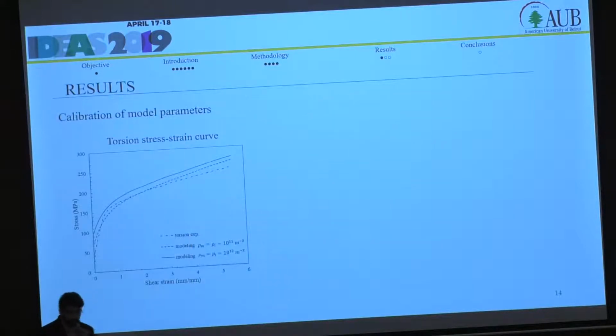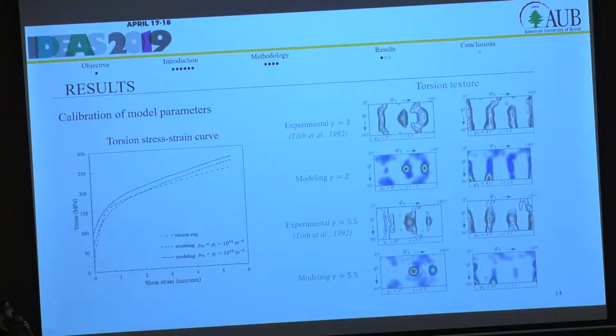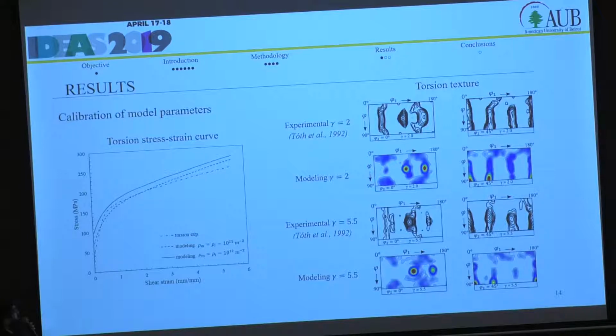Finally, in order to calibrate our model parameters, we have some model parameters that need calibration. Torsion experiments were extracted from the literature, and we compared, for the same material of course, and we fit our model with these data, and we get our model parameters with the best fit.